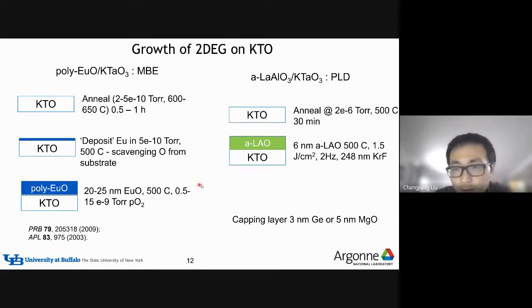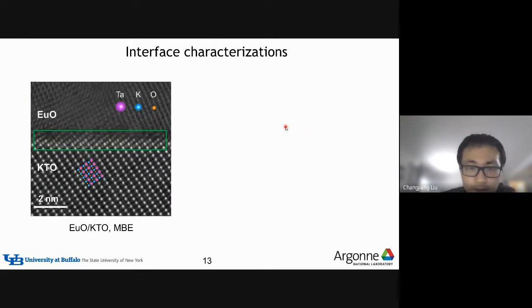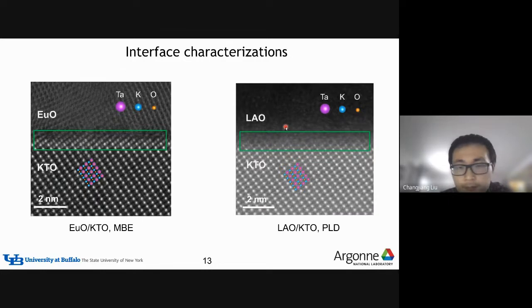So for PLD, we deposit lanthanum aluminum oxide, just like LAO/STO. Here, lanthanum aluminum oxide forms an amorphous phase, but the interface, actually, I will show you, can still be metallic. So after the material grows, we did some characterization using